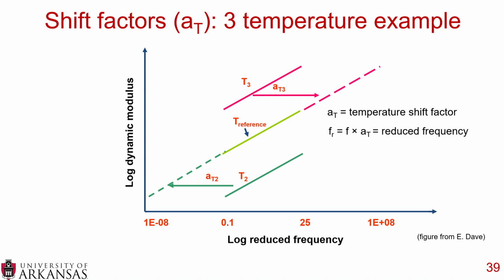And so what we did now is we got a much larger range of frequencies. So you can do much faster loads going over, interstate type loads. You can go much slower loads going over, parking lot loads. This really allows us to explore a much wider range of frequencies by simply using time temperature superposition. And this shifted continuous curve is known as a master curve.